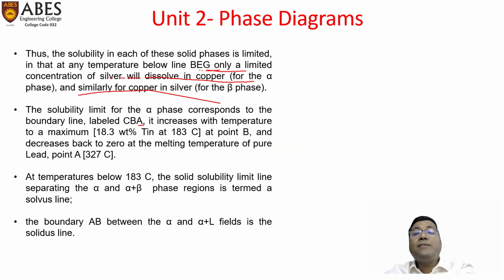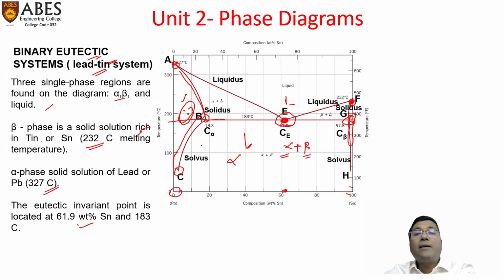The solubility limit for the alpha phase corresponds to the boundary line labeled CBA. It increases with temperature to a maximum of 18.3 weight% tin at 183 degrees at point B, and decreases back to 0 at the melting temperature of pure lead, that is point A. Here we can see the solid solubility line is maximum, meaning roughly 18 to 19% of tin would get dissolved in lead at 183 degrees Celsius. Above this temperature, the solubility will go down and subsequently reduce to 0. It means that at 327 degrees Celsius, no tin would be dissolved in solid lead, and 100% lead would be melting.